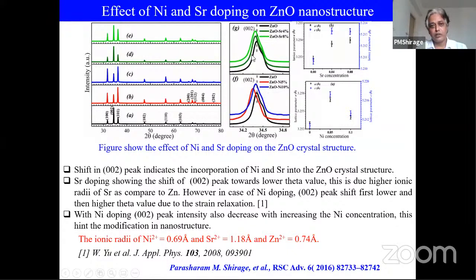For example, look at this replacement of zinc with strontium. This black curve shows pure zinc oxide, and with doping at 4% and 8%, the peak is shifting to lower theta. When we measure the 2 theta, it automatically provides important information on whether the lattice constant is decreasing or increasing. In this case, the lattice constant is increasing because the 2 theta is decreasing to a smaller angle, and we have the Bragg relation 2d sin theta equals n lambda. So the shift of the 2 theta indicates the change in the lattice constant. In the case of strontium, the lattice constant is increasing. It means that we are replacing zinc with strontium.